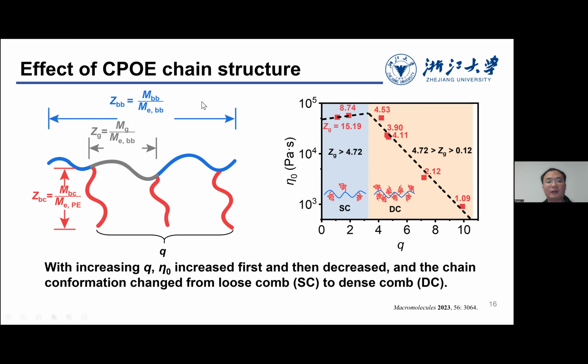And finally, we found that if we increase the number of the side chains, we can go from a loose comb to a dense comb, and the properties are pretty different. For example, in the loose conformation in this area, the backbone and the branch chains possess unperturbed random Gaussian conformation, and the friction between the branch chains is dominant. Once you go to the dense comb structure, the eta 0 will be decreasing with Q, and the dilution effect of the branching chains will be stronger than the friction effect. So the eta 0 will be decreasing with the increasing Q.